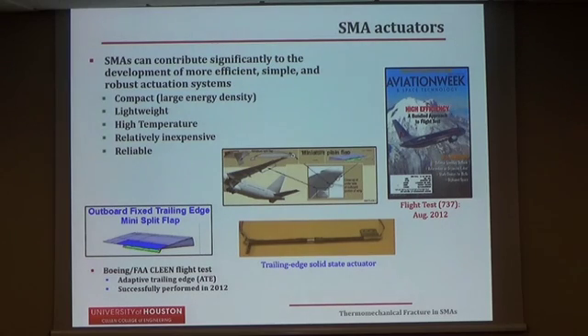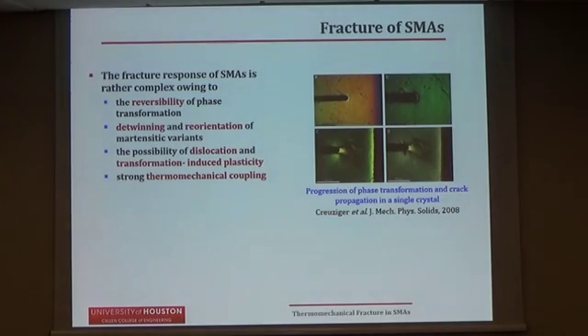A small volume is also an advantage, and thermodynamic efficiency is not essential because, as we know, it takes some time to cool and heat the material. So before moving forward, let me say just a couple of remarks concerning the fracture of SMAs in general. The fracture response of SMAs is quite complex, more complex than that of other alloys, due to the phase transformation, the reversibility of phase transformation, the possibility of detwinning, reorientation, transformation-induced plasticity, and the strong thermomechanical coupling, the rate dependency coming from the latent heat.